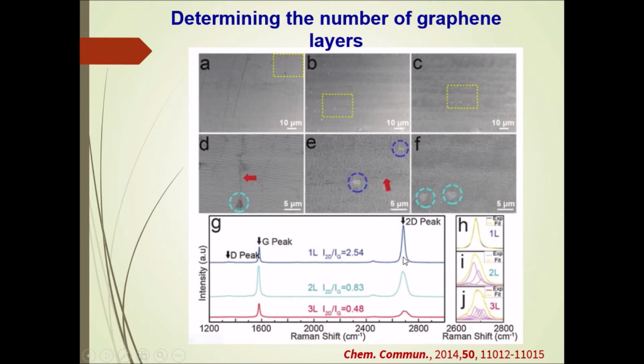In case of monolayer graphene, we can see that the 2D peak is higher than the G peak, and the ratio between them is 2.5. In case of bilayer graphene, the ratio is about 0.9 or 0.8. In three layers, the ratio between 2D and G is about 0.5.